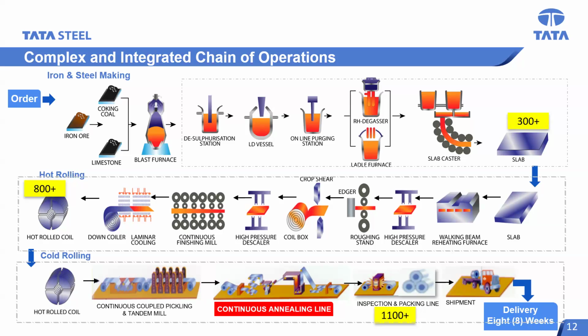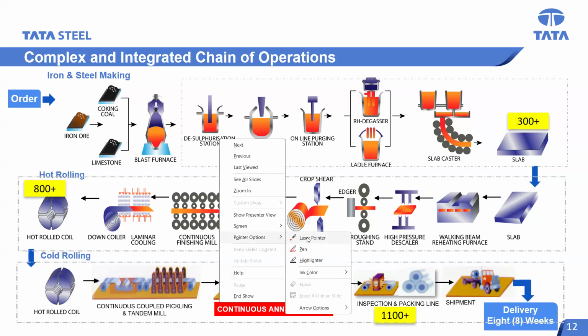The second level of decision making needs to happen at each individual unit process, whether it is steel making, rolling, casting, or annealing. That also needs to take care of the specificities and constraints of that particular unit operation. Here in this project, we developed an optimization solution for the highly value-adding finishing operation called continuous annealing, which is very critical to quality, especially for the premium automotive steel segment. Let me use a pointer first.